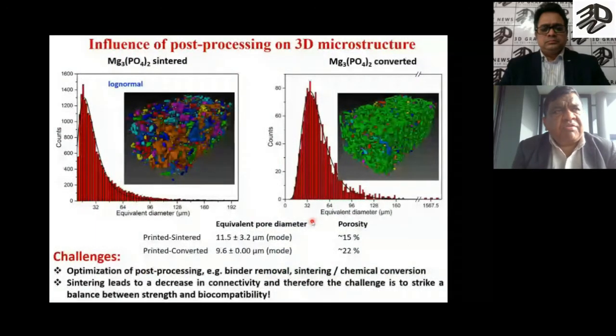Now, one of the important things that we have noticed is that it gives a very highly connected three-dimensional porous architecture. What you see here is the microcomputer tomography image of the three-dimensional porous architecture, where you can see that the equivalent diameter is around 11 micrometer, whereas for printed and converted, the equivalent diameter is slightly smaller, 9.6 micrometer, that is in the mode. When I say equivalent diameter, I'm not talking about the mean, but the peak of the size distribution, more the mode, because this shows a log normal type of distribution.